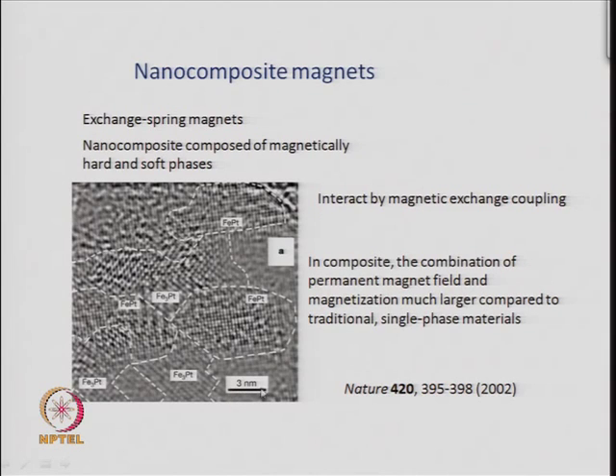As you see, the scale is 3 nanometers. So, you are seeing very, very small regions in these samples, and you have a region which you can identify using energy dispersive X-ray analysis in a TEM. You can find out the composition, that this part of the material has a formula of 1 iron to 1 platinum. So, it is an alloy particle of iron platinum, and this is also iron platinum.